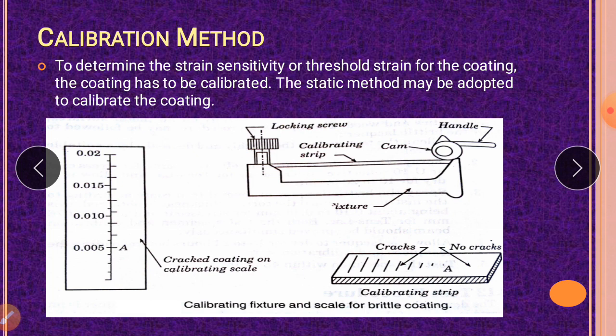The point on the strip at which the crack commences is marked and represents the section where the strains are equal to the strain sensitivity of the lacquer. Since we are using the aluminum strip, which has some strain, it is equal to the strains developed in the coating. That is how it is calibrated. The calibration strip can then be removed from the loading fixture and placed alongside the calibrating scale, from which the incipient crack strain can be read. So we can read the crack strains.